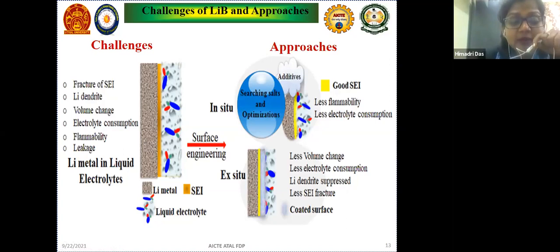it saves the electrode from the short circuit. But when there is a poor solid electrolyte interface layer, or there is a fracture in the solid electrolyte interface, then definitely the lithium dendrite causes the short circuit.